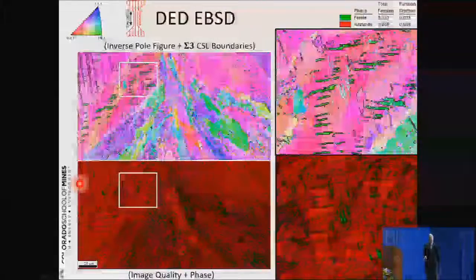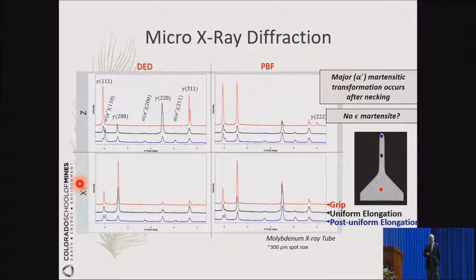But the X-ray diffraction shows you the best examples. Look at here, there are three different spots where we did the X-ray. One is from the grip, one is from the uniform elongation side, and one is from the post-uniform, the non-uniform elongation. So let's focus only on the blue ones, okay? If you look at the blue one across here, the DED, direct energy deposition, and the powder bed fusion, they all show the presence of martensite.